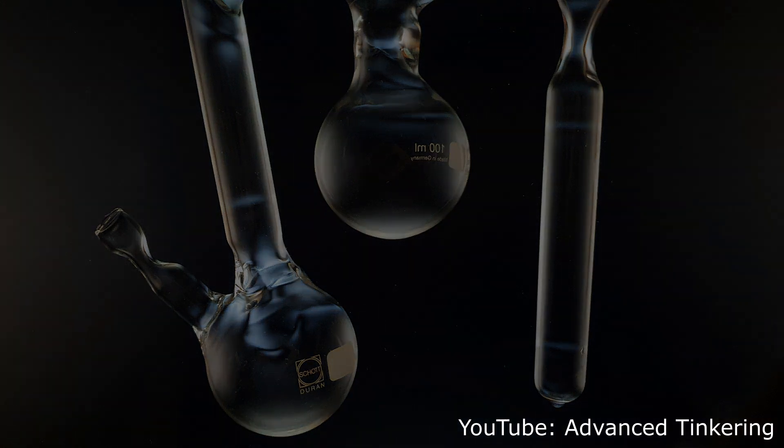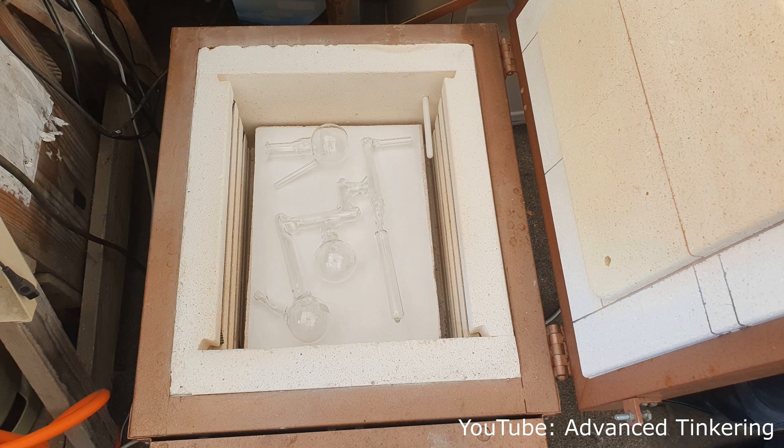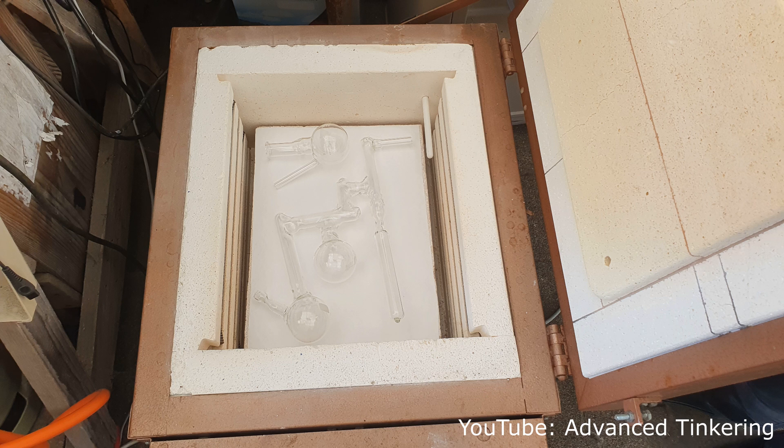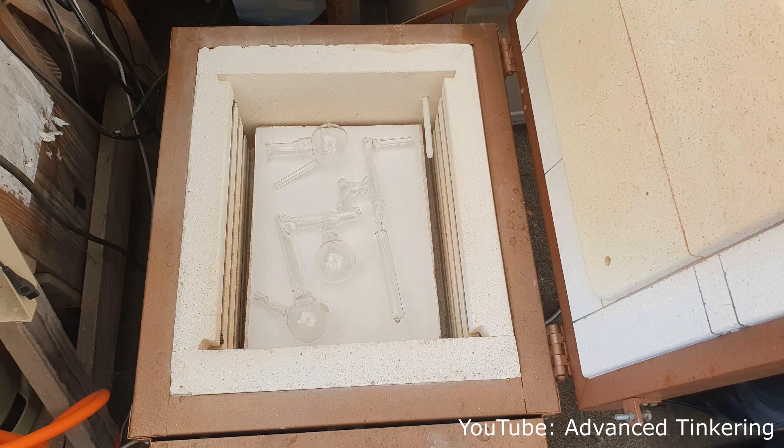To reduce the stress, I annealed the glass in a kiln. In this kiln, the glass gets heated slowly to around 550 degrees C, was held there for around an hour and after that it was cooled down slowly.